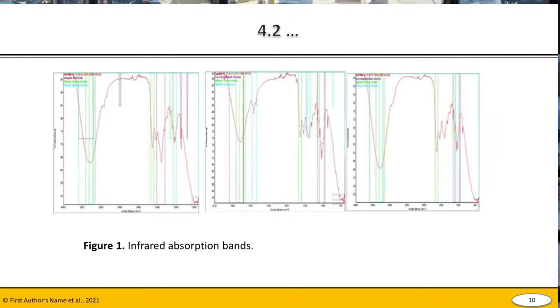IR spectroscopy was used to study the chemical composition of the finished samples. The study was conducted to analyze organic compounds and determine their structure. During the test, it was found that all samples contain primary aliphatic amides in the range of 1,600 to 1,080 centimeters to the minus 1 power. Please, next slide.